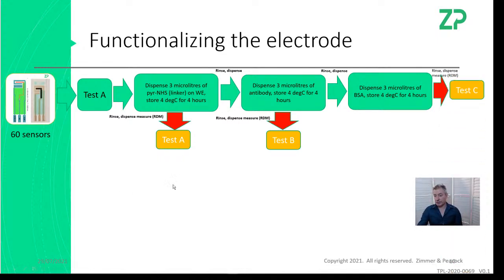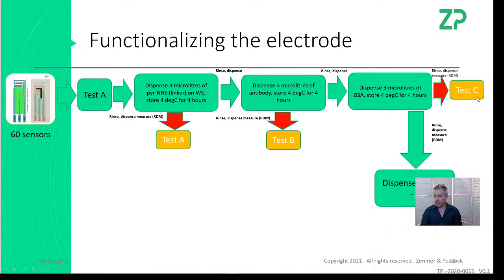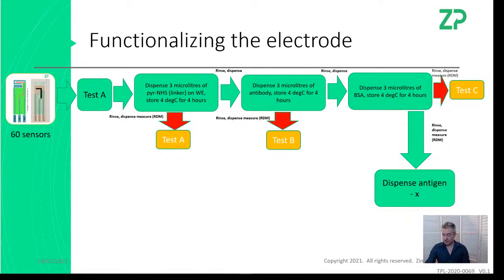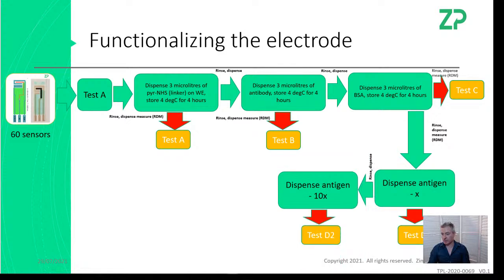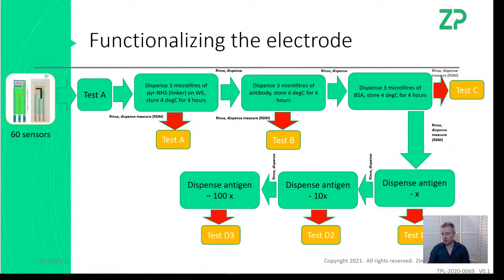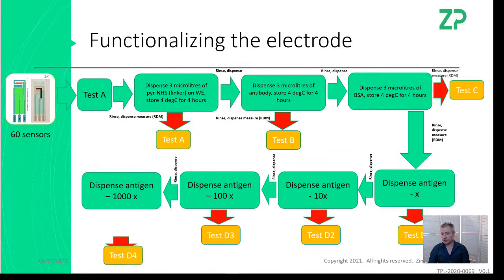So every time we do a test, we're probably sacrificing like 3 electrodes. So we started off with 60 sensors. We took it down to 57, took it down to 54, took it down to 51. And now we're adding the antigens. Now this is when we actually start doing the test itself. We put on some higher concentration of antigen and we test those. We put on a higher concentration of antigen, we test those. Put on a higher concentration of antigen, we test those.